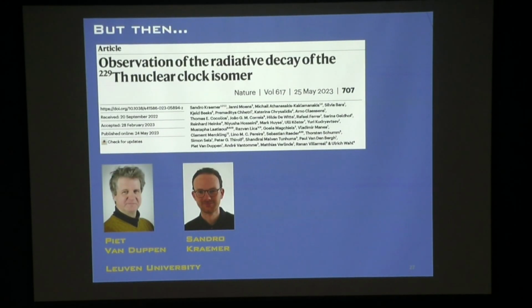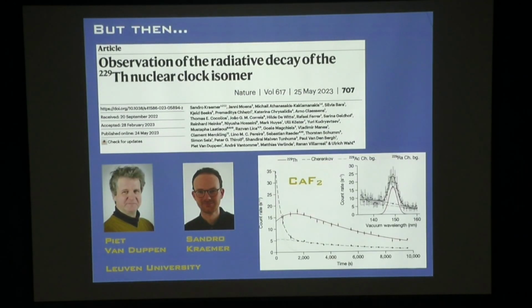Actinium-229 will beta decay into thorium-229. And the choice of actinium over something like uranium, which is what people had done before, was brilliant, I think. When uranium decays into thorium-229, it's an alpha decay, and it just wrecks the crystal. But a beta decay is a much softer thing. And so what he then saw was, if he took these samples after he placed actinium in them and some of them convert to thorium, when they convert to thorium, there's a decent fraction that convert to the excited nuclear state as the gammas just rain down. And so then he just looked to see if any VUV photons came off of the crystal. And sure enough, they saw a few nanometer wide signal around 150 nanometers.